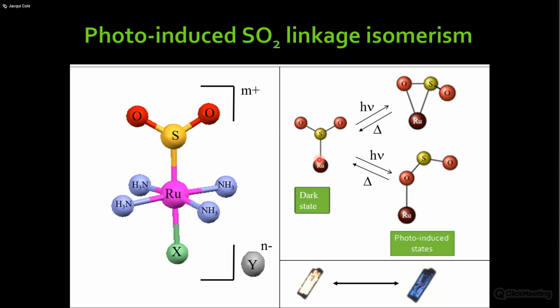So it goes from sulfur bound, you see on the right there, to either a side-bound form here or actually the oxygen-bound form here. And so there are potentially up to two photo-induced states that you could obtain. Of course, that's quite difficult to see in a single crystal when you model it. So you may see these overlapping, almost looking like a disorder type problem. But if you're lucky, you'll get a clean transition. And then you can reverse it by heating it up, right? So if these are photo-induced at about 100 Kelvin, then you can heat it up to get back to the